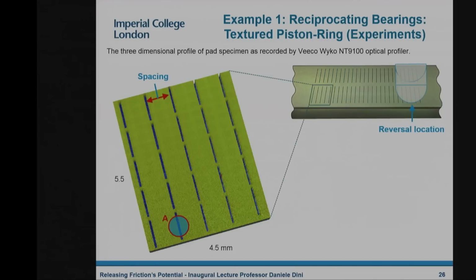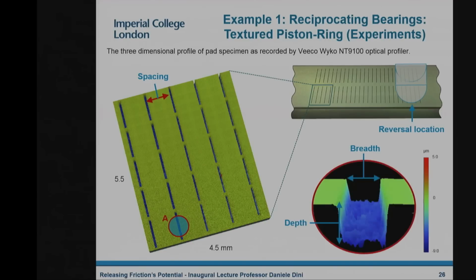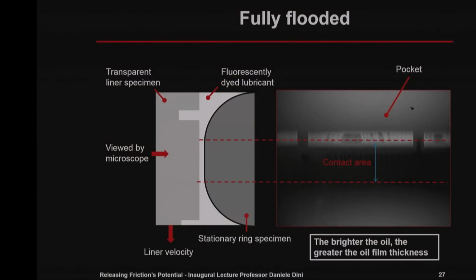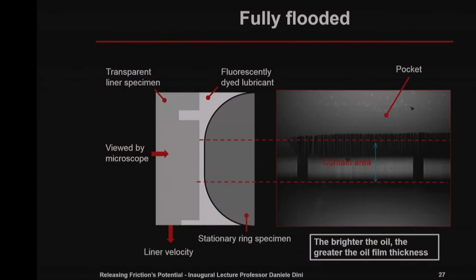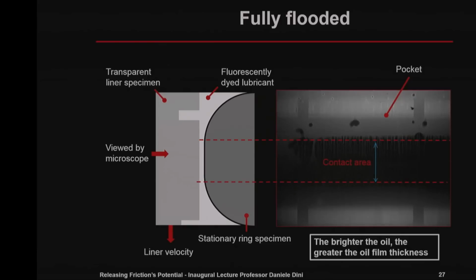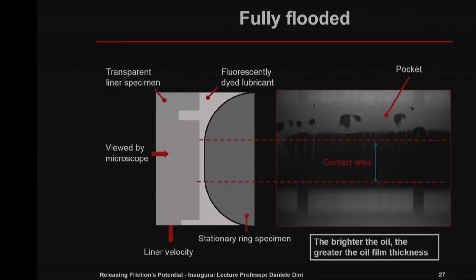And the response of what happens very much depends on what you do to these surfaces. And here we're talking about looking at the microstructure of these systems, where we're talking about pockets on the order of micrometers in size. So we're talking really about how a micrometer-sized pocket can change the behavior of this system. And I set out to explain this by, first of all, looking experimentally at what you see. If you look through these surfaces, so let's say your sapphire window is here, you look through the surface, and these surfaces are moving with respect to each other. If you monitor this, you see that there is interaction between the pockets and the fluid.